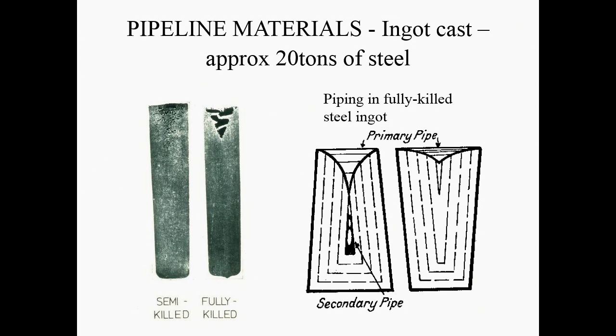So you have to generally heat the steel in a furnace at a high temperature to normalise the composition. That means homogenise the composition to make it the same throughout the whole of the ingot. So this is the primary casting, and then there will be a heat treatment process, and then there's your rolling processes. If you've got a semi-killed steel, you often get this secondary pipe, because again this is freezing, and this bit's been freezing faster than this bit because of the shape of the mould, you can see here, and you end up with a sort of defect right down the middle of the ingot. And this is the origin sometimes of defects that you'll see in pipe steel.